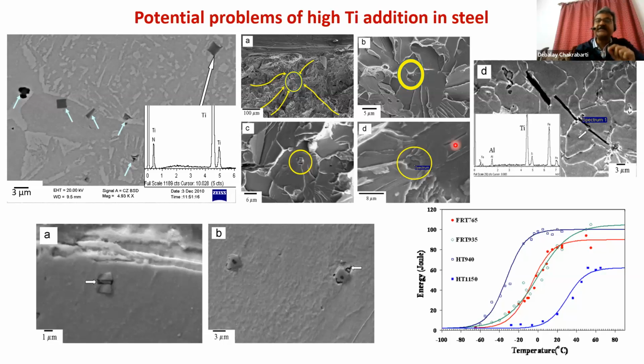So what can happen is, if we add titanium at a little higher level, more than 0.08%, typically titanium segregates and forms very coarse titanium nitride. These titanium nitride particles act as crack initiators. You can see in this image how the particle is initiating cracks, either by cracking themselves or by separation of the interface, and the impact toughness can become much poorer.